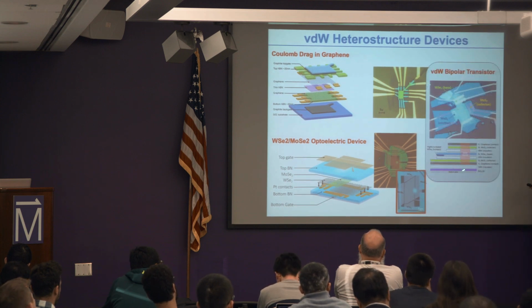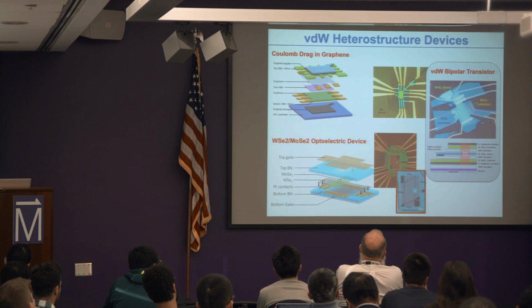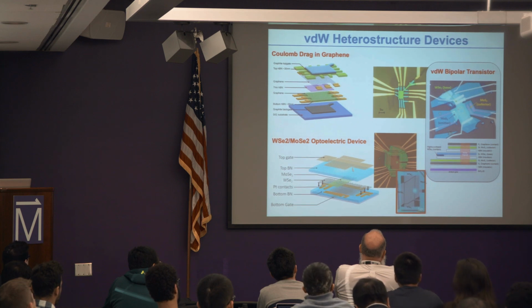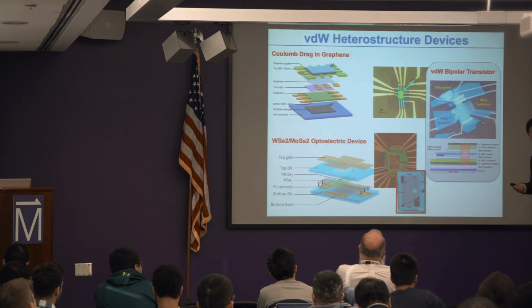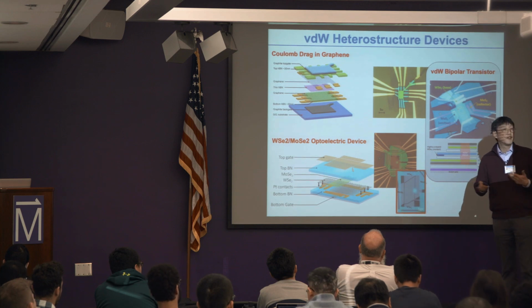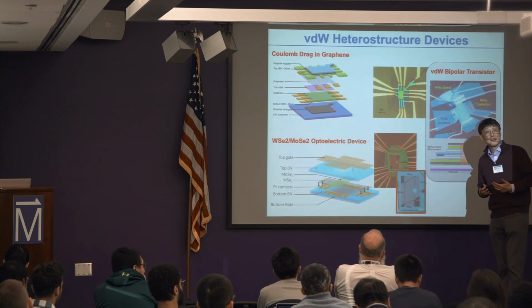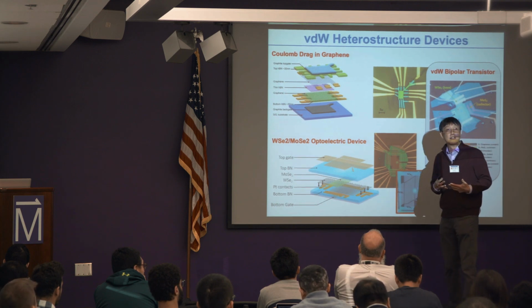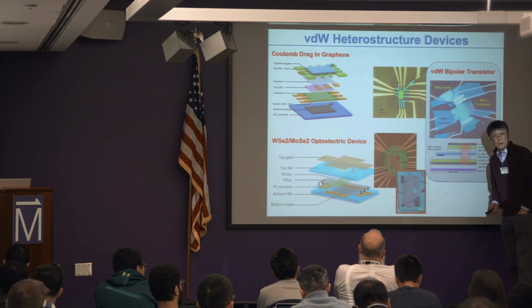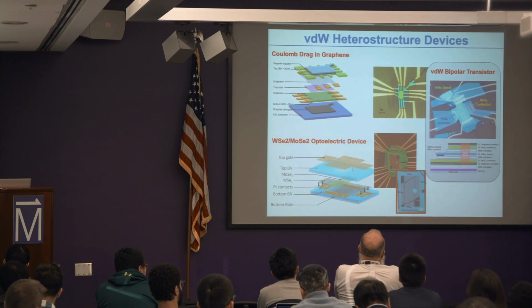Perhaps the most impressive example here is 9 layers of stacking, and there are 6 electrically active layers. All of these layers are individually contacted in this type of device. The device itself is a P-N-P type bipolar transistor. But nevertheless, experimentalists can make such complicated geometries with many different contacts on this device, which allows us to make rather complicated devices out of this type of heterostructure. That's one of the experimental advantages it can present.